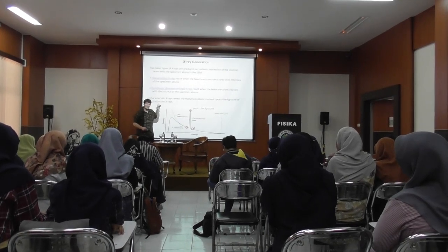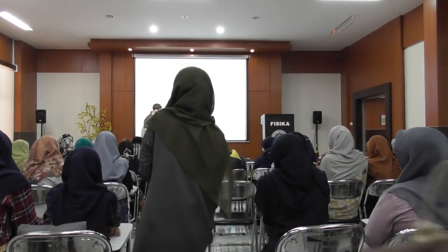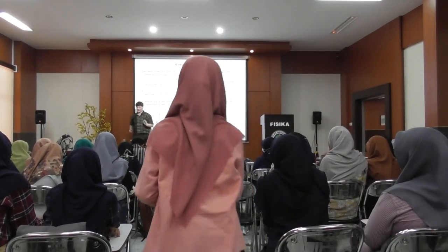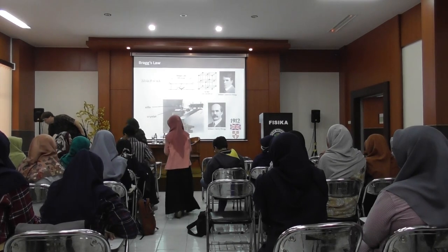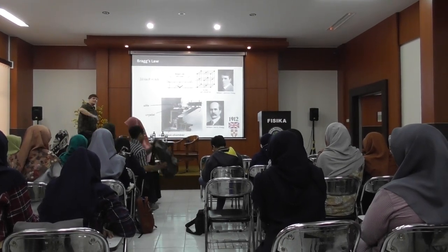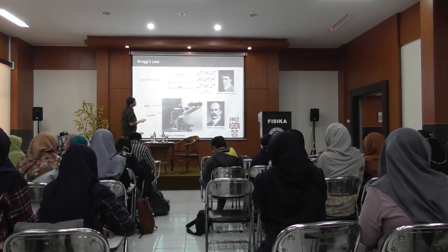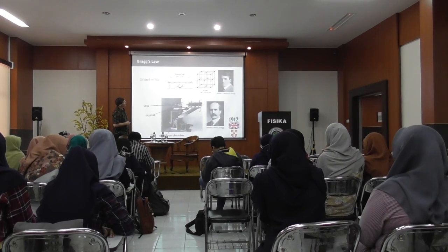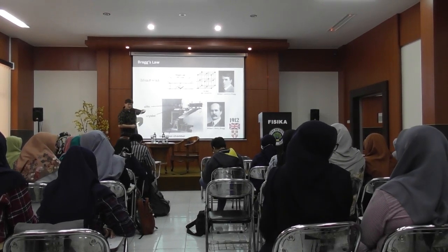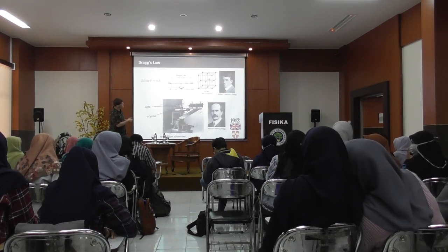So how do we do that? How do we do that? Exactly this energy of X-ray. Well, we use the wave theory of light. Light's a wave. It's not just a particle. It's also a wave. And so we can use Bragg reflections. We use crystals. So crystals have parallel planes where you can set up constructive scattering using Bragg reflections.